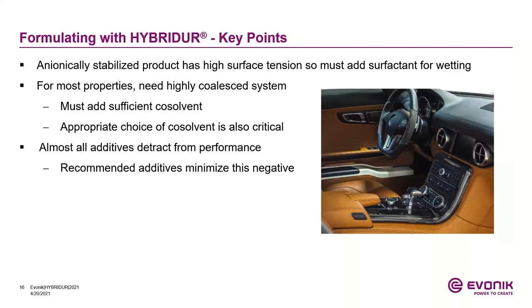In the next few slides, we will look into different coalescing solvents that can be used with the Hybridurs. We must add sufficient co-solvent to get good coalescence. Appropriate choice of the co-solvent is also very critical. The choice of additives is very important. Almost all additives, if not formulated properly, detract from the performance. And so we recommend a number of additives for formulating with Hybridurs. And as long as those additives are used, it minimizes the negative effects of detracting from the performance of the Hybridur polymer dispersions.